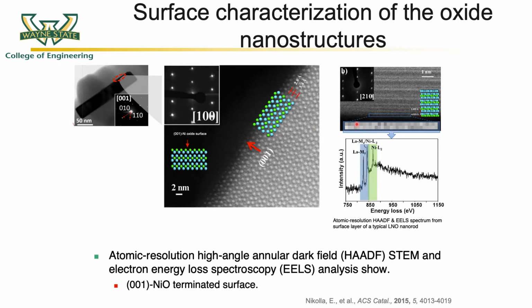Upon EELS measurement of the near surface region, a nickel-rich region is found, suggesting that the surface is actually terminated by the 001 nickel oxide, which is the catalytically active surface.